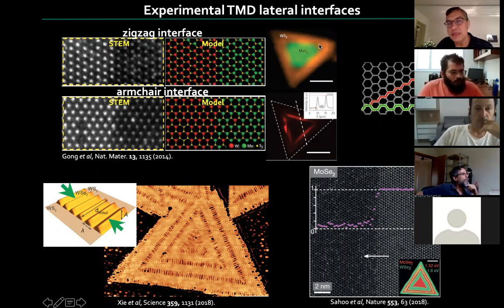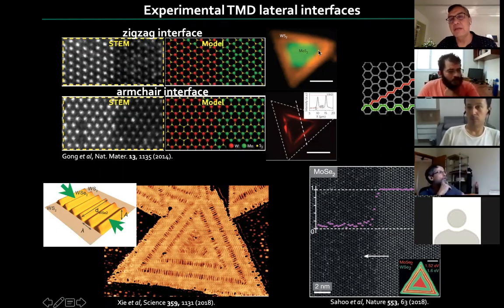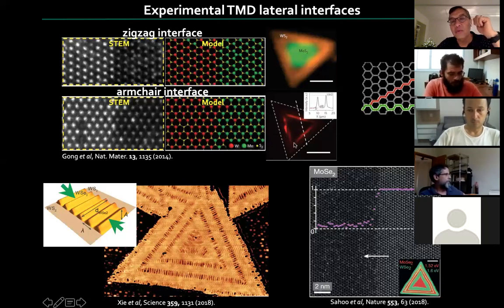And here on the right, what you see is photoluminescence data of such an interface. The middle part of the grain is molybdenum sulfide, the outer is tungsten sulfide. And you can see that the photoluminescence has different colors because, of course, being different composition, it has different gaps for the exciton. So they can subtract off the two peaks corresponding to these colors. And what you end up with is another luminescence that is right there in the middle, as you can tell. And that tells you that, in fact, that interface behaves differently, right? It has its own exciton. It has its states that live right at the interface.